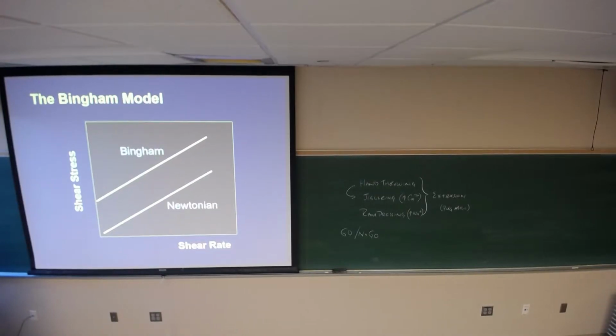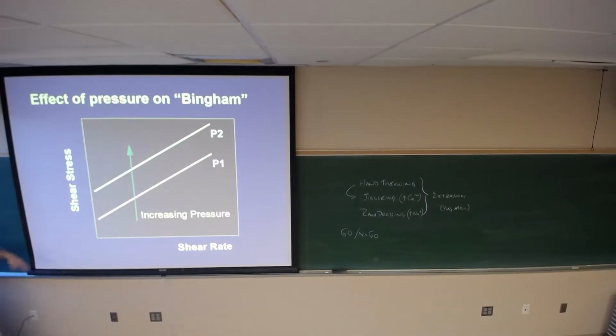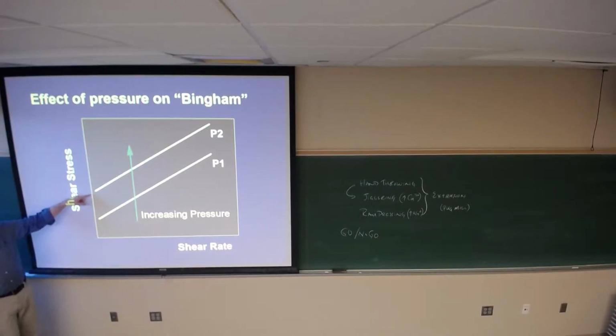So we get essentially this. We said that this is a typical rheological response. You have a Newtonian behavior, you have a Bingham behavior like ketchup. But plastic bodies actually exhibit Bingham behavior. So what you get is a linear increase in shear stress with shear rate, but you have a yield stress associated with that. And then we would argue that as we increase pressure, this yield point here increases with increasing pressure. But what would likely happen is that the slope would stay the same. Okay, you would increase that. And then what we can do is plot this yield stress here as a function of pressure to look at the behavior of these materials.